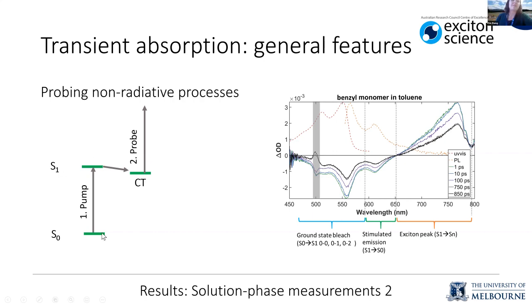So I just tried to show that if you pump your sample up to the S1 and then you illuminate it with a second source, your probe, then you can measure the absorption of that, for example, charge transfer state. So that's what we're looking at here. And then sometimes there are weird squiggles that are to do with the pump scatter. So I'll try and point out when that's happening as much as possible.